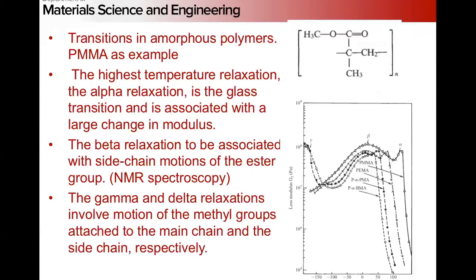So if we consider just an amorphous polymer, we'll use PMMA as an example. It's common convention in the polymer literature to label these transitions as alpha, beta, gamma, delta, basically alphabetical Greek order. The alpha relaxation is the glass transition, which gives us our large change of modulus. The beta relaxation has been characterized typically by NMR spectroscopy, with side chain interactions associated with this ester group, and the gamma and delta relaxations have to do with the interactions between these methyls.